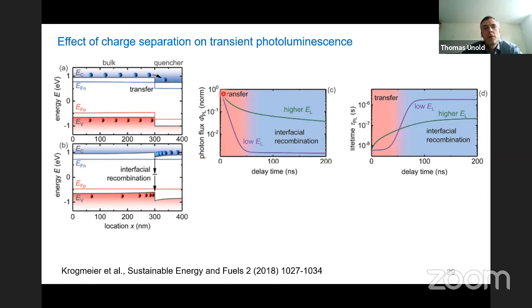If you use a lot of light, then it takes actually a long time. You have this charge transfer, but I mean, you don't reach a steady state until long times. So if the injection is low enough, then you have this transfer of charge carriers, and then you reach the steady state condition of interfacial recombination.